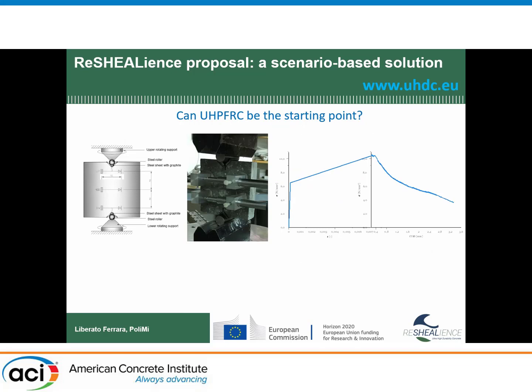Well, actually you cannot see the numbers, but the tensile strength is about 8 to 10 megapascal. And we have a strain capacity of around 1%, which is quite good for the applications that we had in mind at the beginning. Actually, we are going to compare these results from the back identification with the results that we are obtaining with this double edge wedge splitting test that we have developed in Milano. And we are demonstrating that applying a compressive stress, because of the geometry of the specimen, you directly get the tensile stress-strain law. So you do not need the back analysis.